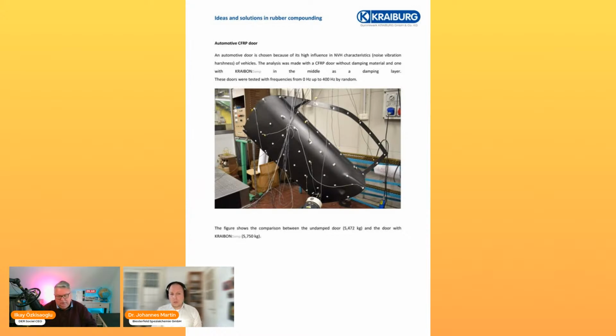And yes, you need to increase the weight a little bit, but compared to traditional methods like aluminum butyl or very heavy acoustic foils, which could have a weight up to, I don't know, 4 kilograms per square meter, we are talking here about a fraction of the weight. And you see that this was a test where we measured the frequency between 0 hertz and 400 hertz.